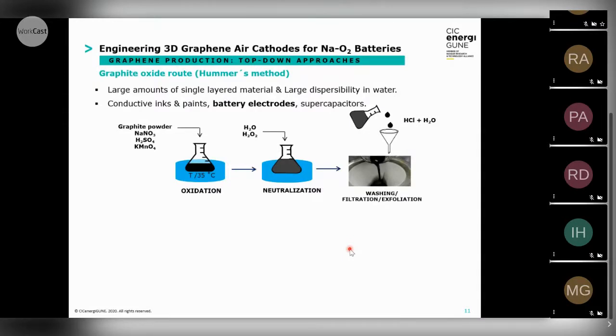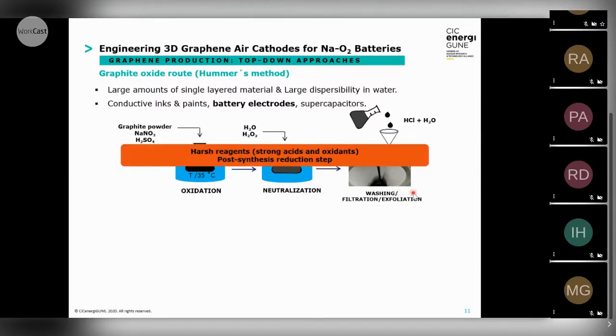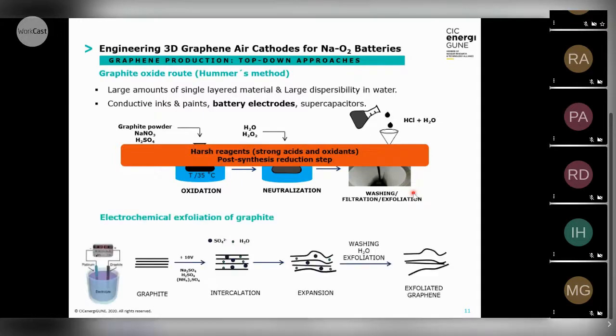First, by the so-called Hummers method, where we can see here all the procedure to oxidize the graphite, and then to neutralize and finalize to get the suspension by washing, then filtrate and exfoliate. But this method is using really harsh reagents such as strong acids and oxidants. And also, we always need a post-synthesis reduction step. So the second approach that we have followed is to electrochemically exfoliate graphite using a solution where you can intercalate these anions and the water, expand this graphite sheet, and then finally get this exfoliated graphene.